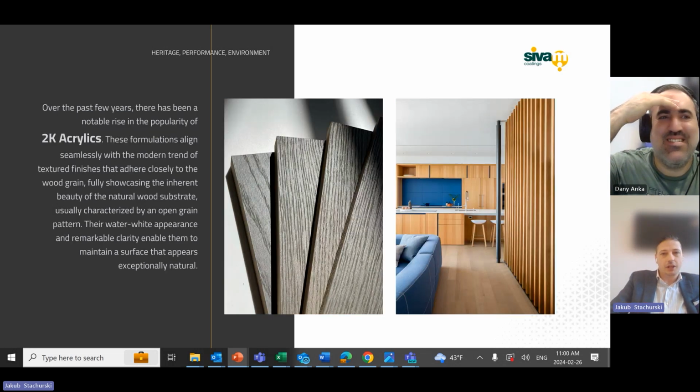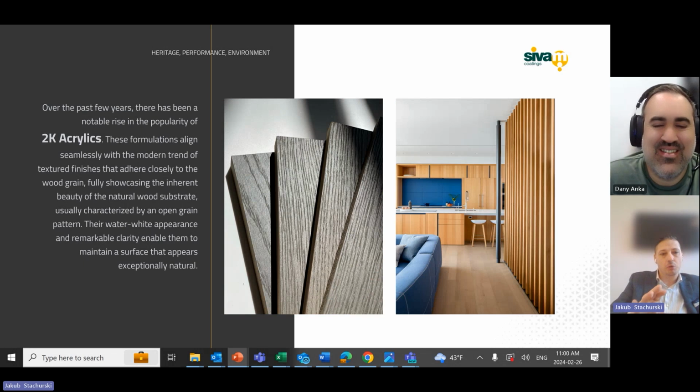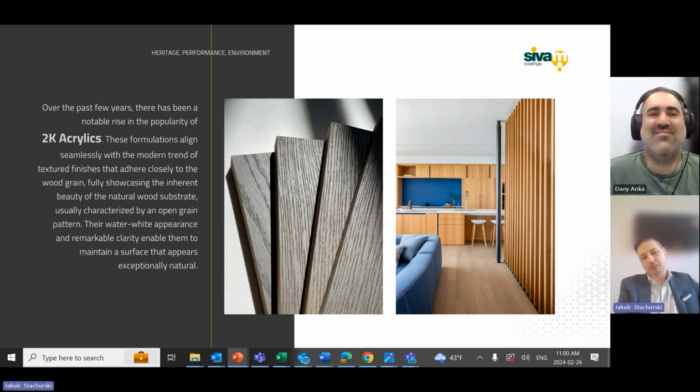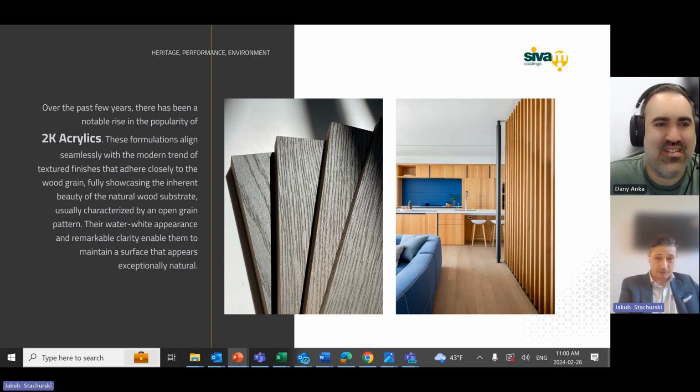in the wood and the finish, where acrylic urethane will remain cool and more true to the wood itself. So we also see a lot of applications on these man-made recon veneers, whatever name manufacturer will assign to it, or bleached looks. That's when we will see acrylics, because they will retain that look, and they will not yellow over time. And a lot of times these acrylic urethanes will also have UV inhibitor built into it, which protects the substrate itself from yellowing further.